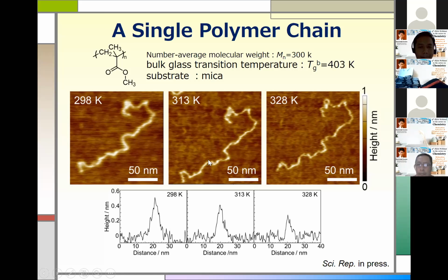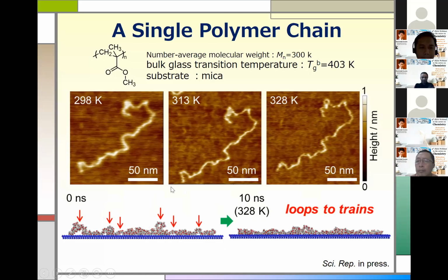I'm gonna show you the cartoon later on, but we just look at the cross-sectional area of this single chain. See here, this is at room temperature, but with increasing temperature, this cross-sectional area is gonna decrease. And with increased temperature, this is gonna decrease faster. Then what is going on with this transition is like this. At the beginning, we have this kind of loop conformation, but eventually this is gonna be collapsed like this. Then we see this kind of clear shape. Now we also take a look at this part, and with increased temperature, this part moved like this. And this part further moved like this. So what I can say from these images is that we are directly able to see the movement of a single polymer chain. That's what I'm saying.